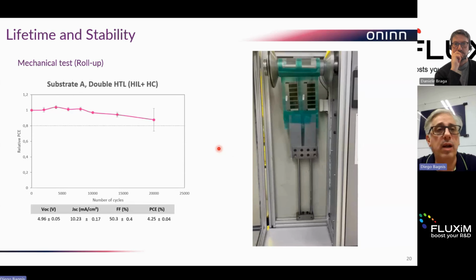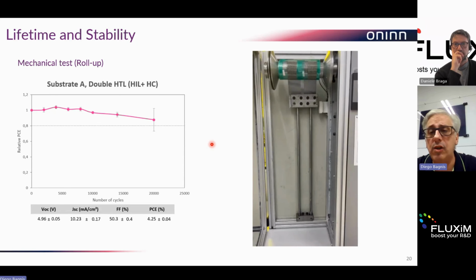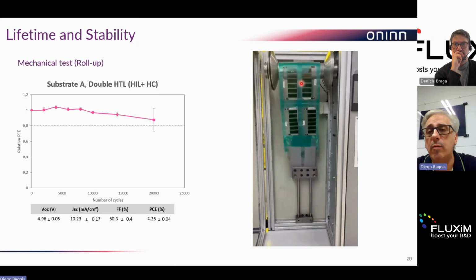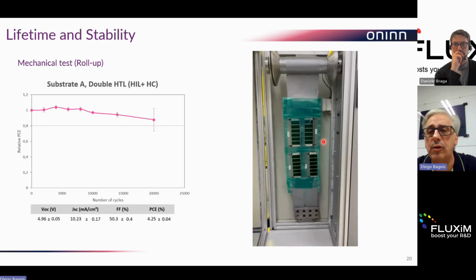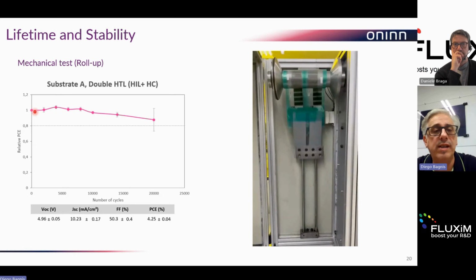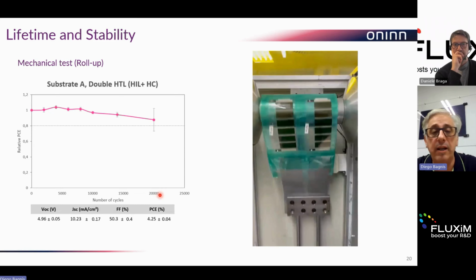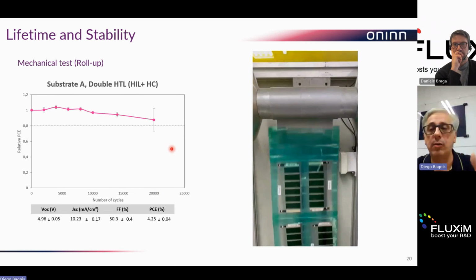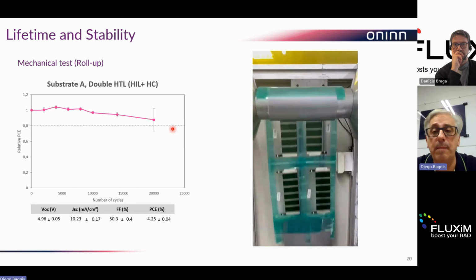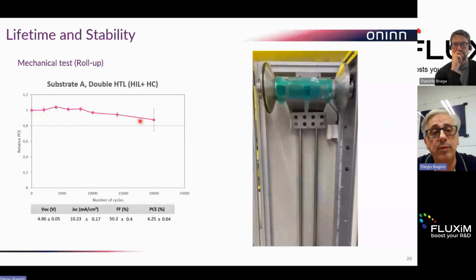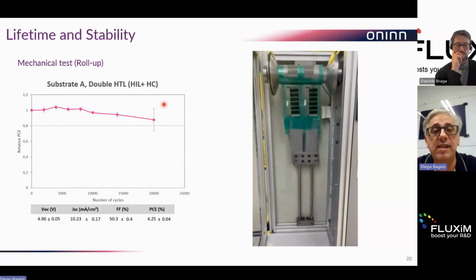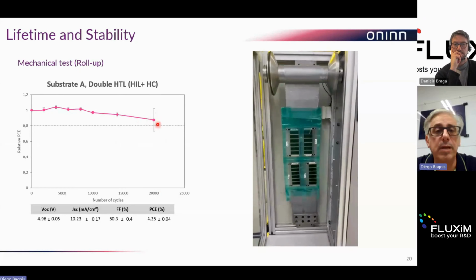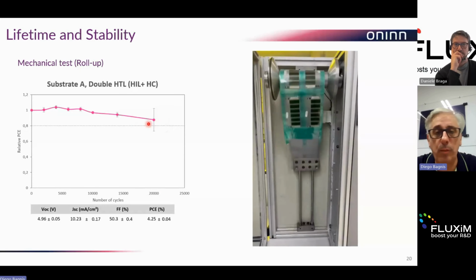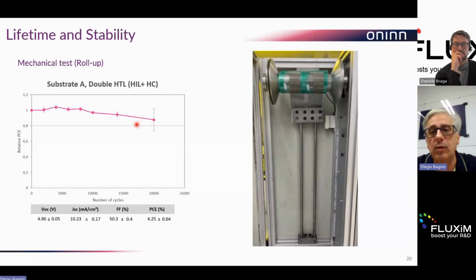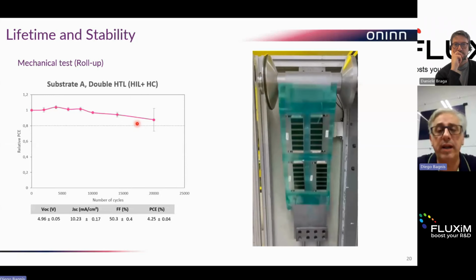If we move to lifetime and stability, for example the mechanical stress test, for some kind of application, this is equipment developed internally, where we stress from one side to the other side, so the maximum stress possible, on the mini module. We see that after 20,000 cycles, where you stress the mini module much more, the performance is pretty similar to the beginning, maybe just at 20,000 cycles we see a slightly higher drop. But in general, the optimization of the encapsulation and all the layers is pretty fine in this kind of development.